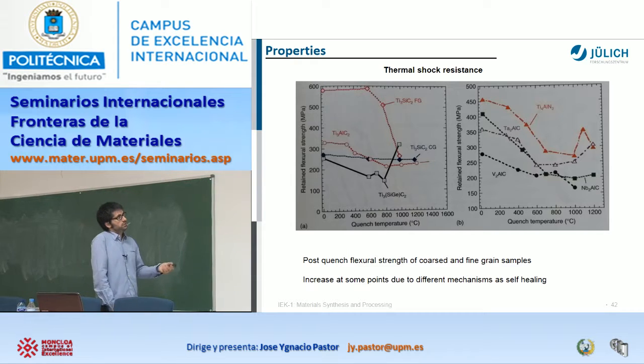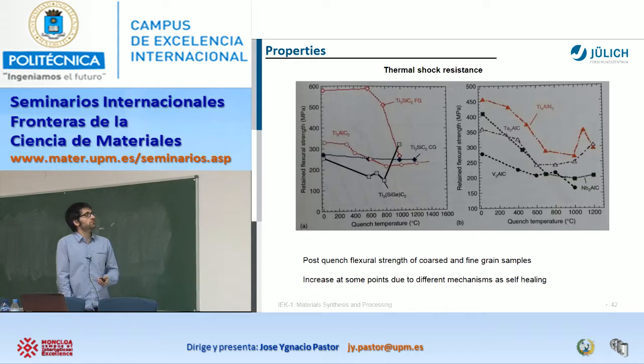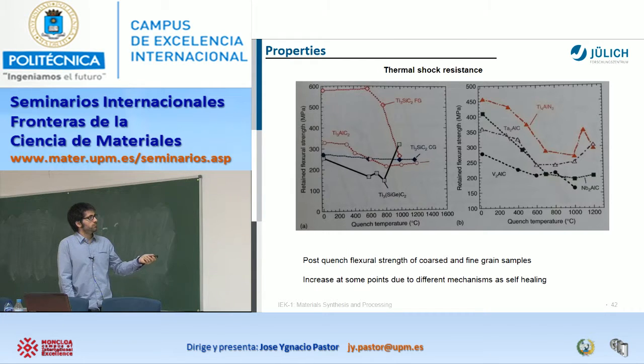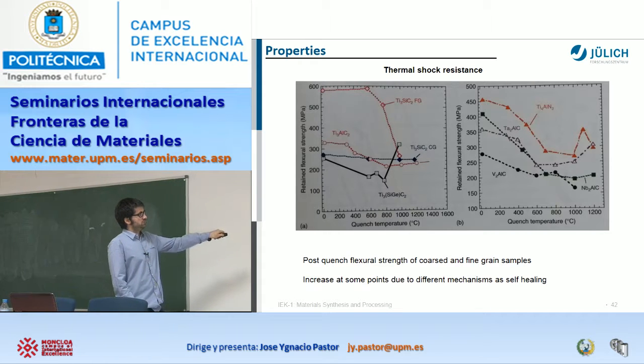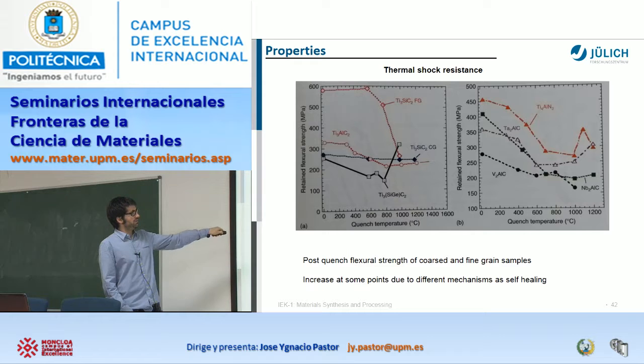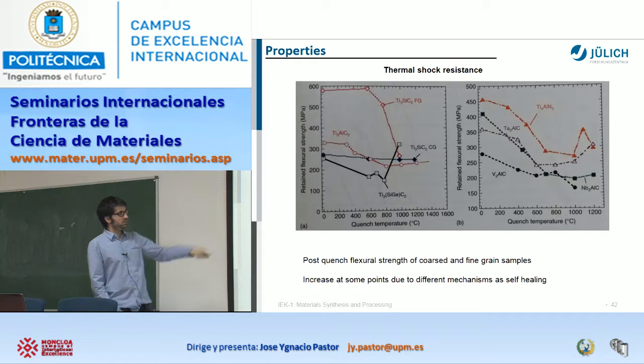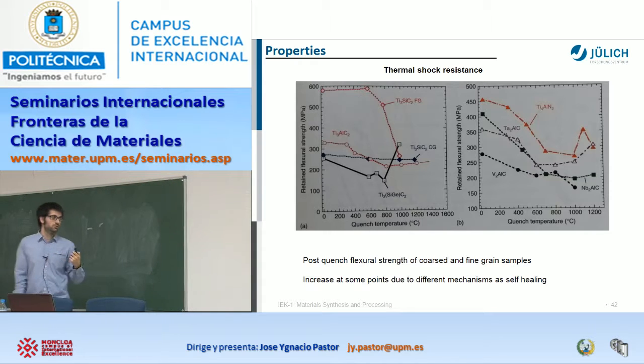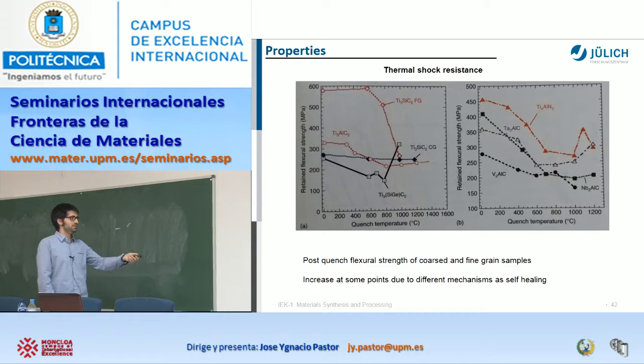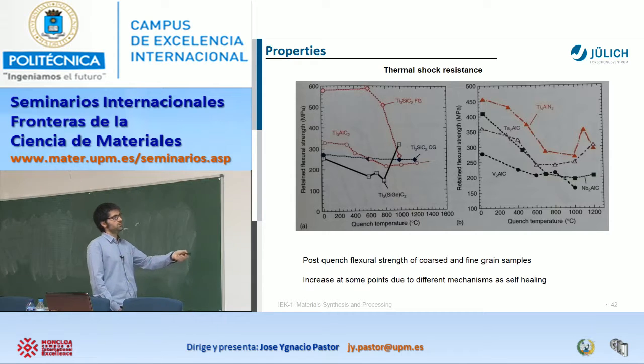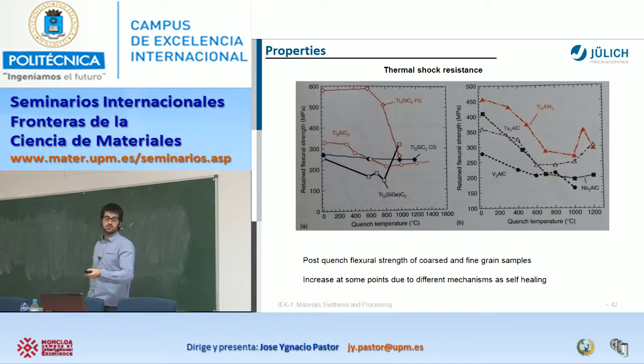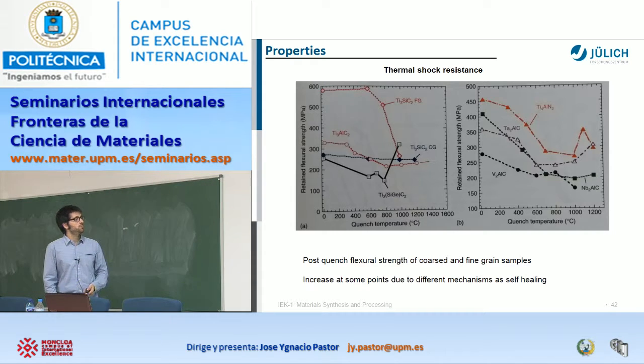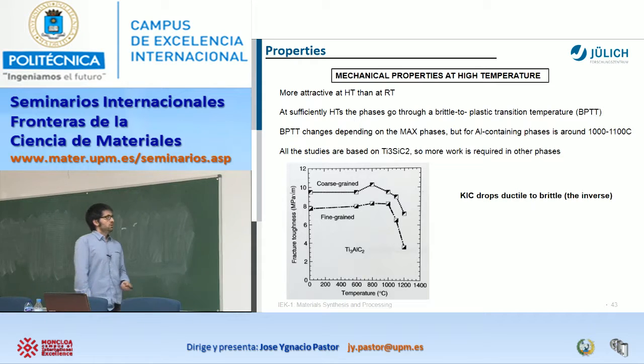Okay, and well, as you see here, it depends of course on your grain size, but they can, for example, in that case survive several quenchings at really high temperatures. Okay, and it's important to see, for example, this increase also at really high temperature. It's like that, and after the increase, or here, and this is due to this self-healing effect that we have talked about. They even respond better at really high temperatures than at intermediate temperatures, because at really high temperatures what you form is the healing of these micro cracks, and then your material at the end will have a better response. Okay, and it's quite interesting, but unfortunately there are not many works on that.